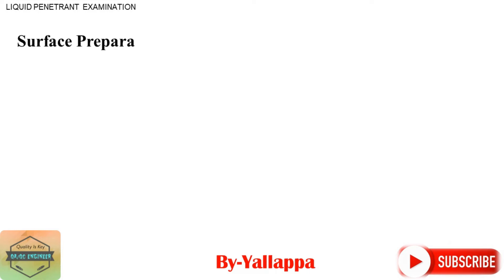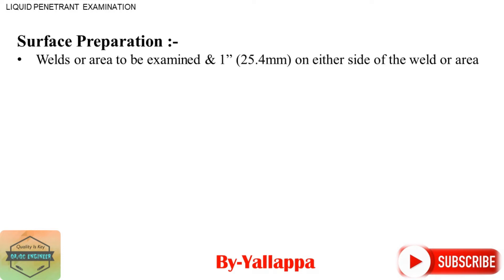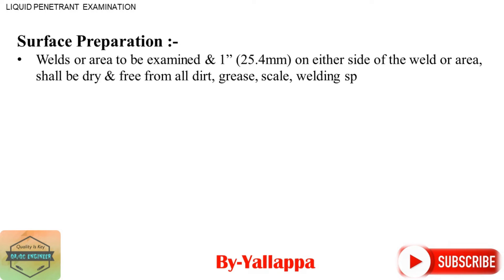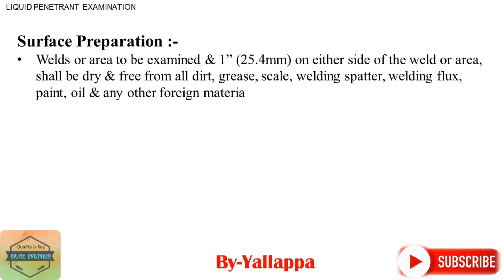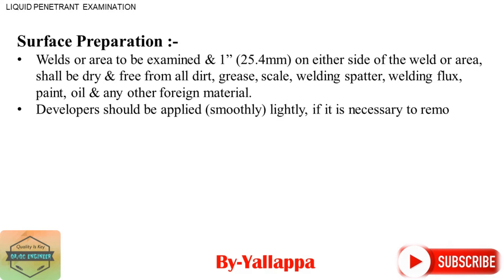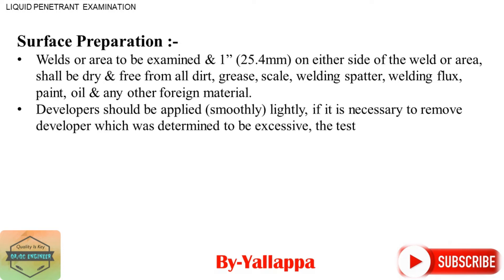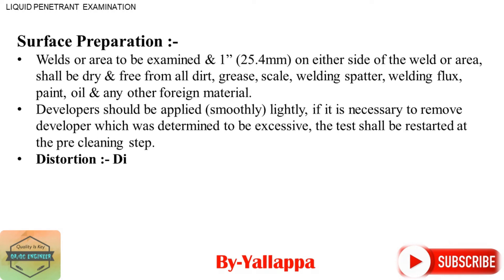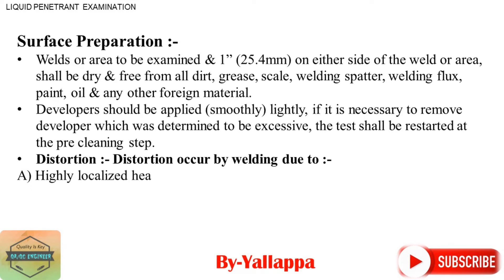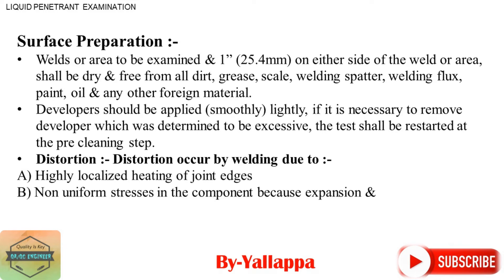Surface Preparation: Welds or areas to be examined and 1 inch (25.4 mm) on either side of the weld or area shall be dry and free from all dirt, grease, scale, welding spatter, welding flux, paint, oil, and any other foreign material. Developer should be applied smoothly and lightly. If it is necessary to remove developer determined to be excessive, the test shall be restarted at the pre-cleaning step.